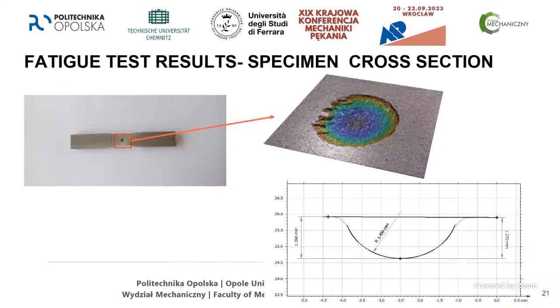Beside this, we have also performed a cross section of the whole sample, right? First of all, we cut it through. You were expecting maybe there's nothing there. Maybe our partners didn't leave the powder inside, but as the scans proved, it was also there. It went outside after we cut it through. And this is the surface that you can see with the use of specialized software. The machine is called Sensofar, and this is used in order to calculate the height, the roughness of surfaces, to measure areas, and so on.